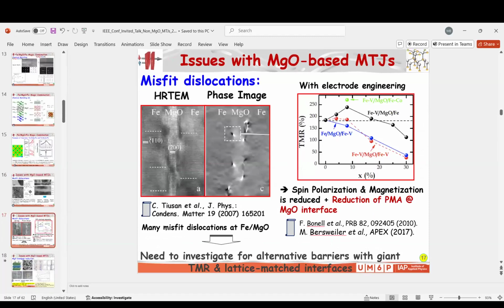This is another study about the dislocation. For example, for the phase image, this has been done by the Nancy group in France, and they try hard to overcome this. The solution provided is to dope iron with vanadium. This is one way to lower the misfit dislocation and the lattice mismatch. I remind you that the lattice mismatch between iron and MgO is about 3 to 5%. And we are going to see, in the case of spinels, this will be reduced to less than 1%.